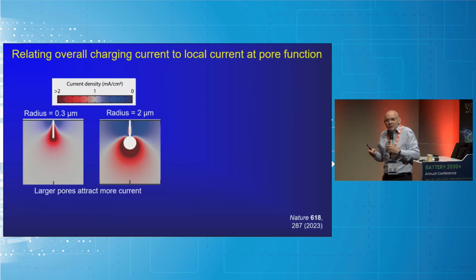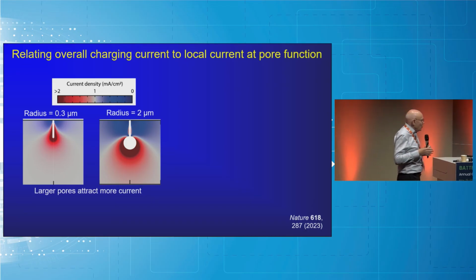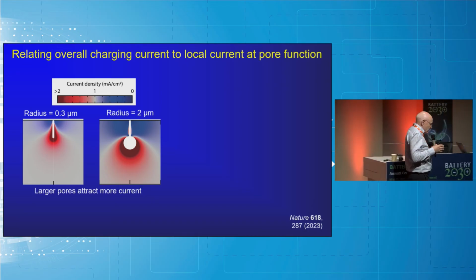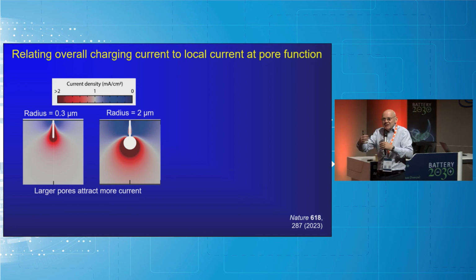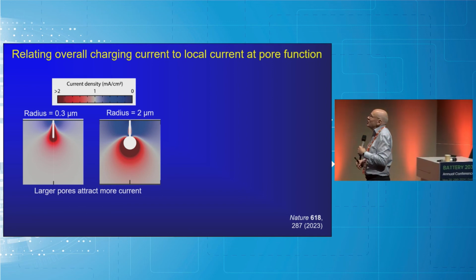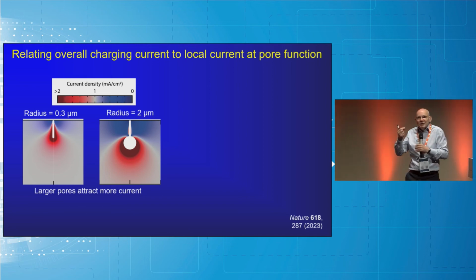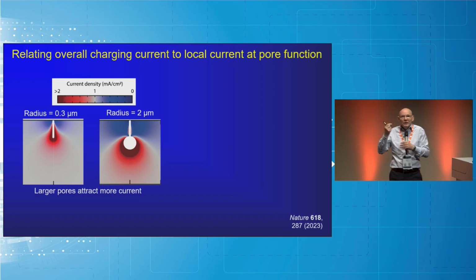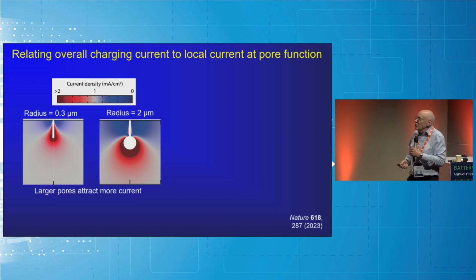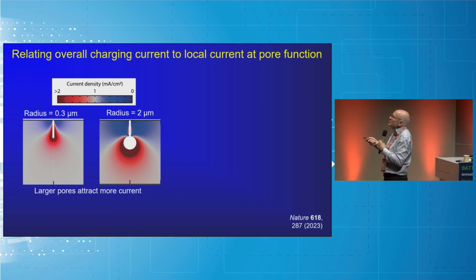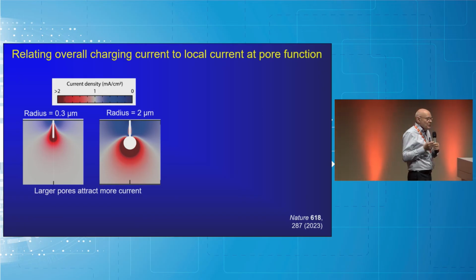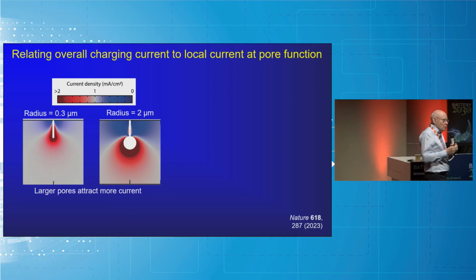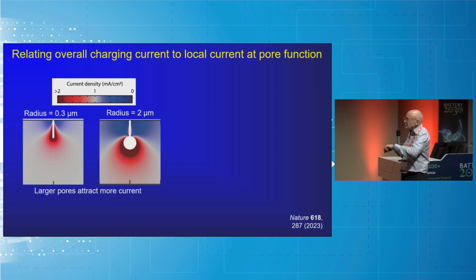So what we wanted to do then, of course, that's the physical model. We then wanted to relate the applied current density, the milliamps per square centimeter you're charging, to the flux of lithium going into the pores, in order to really be able to model at what applied current you're going to start to get a dendrite. So you have to take account of a few things. First of all, that these pores are small, so you get field enhancement, current focusing, as you would normally get.